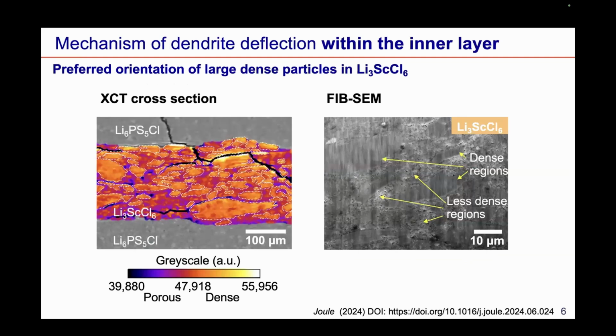The XCT cross-sectional image of the lithium scandium inner layer is colorized to enhance the contrast. The heterogeneous nature of this inner layer is very obvious. These orange regions are more X-ray attenuating, indicating that these regions are denser than their surroundings. So this suggests that there are numerous large dense particles separated by porous regions. And this microstructure is also apparent in this focused ion beam SEM cross-section, as shown in the right figure.